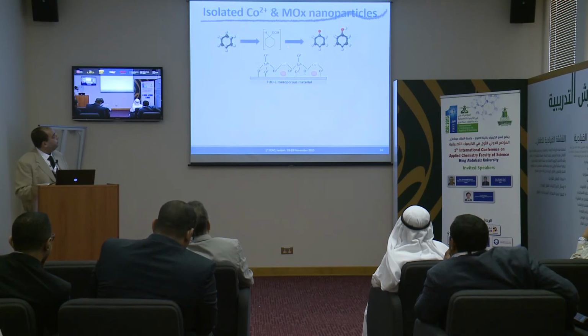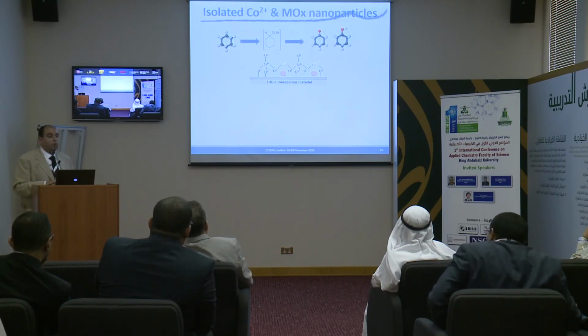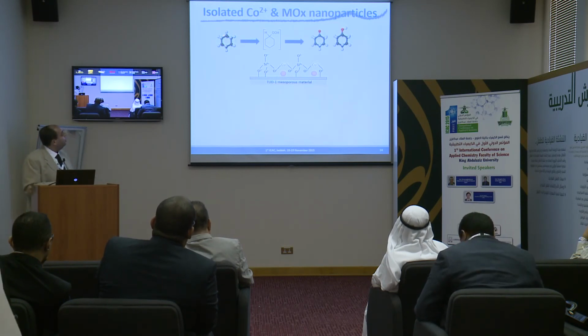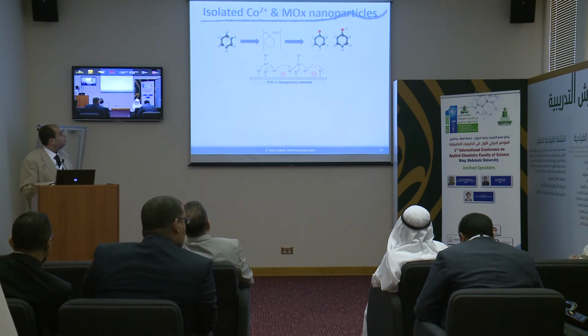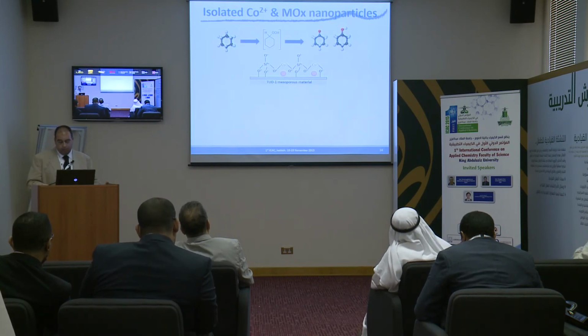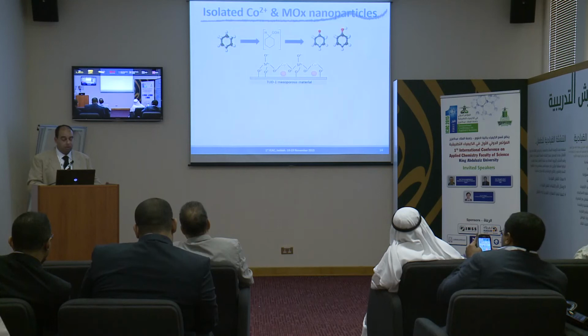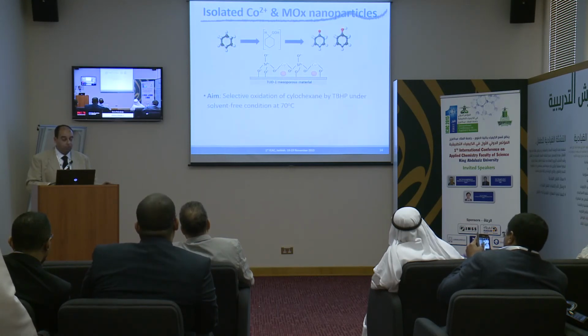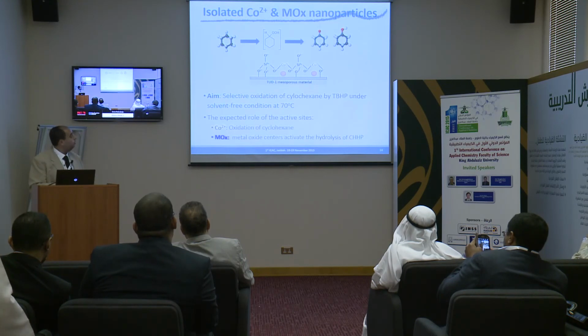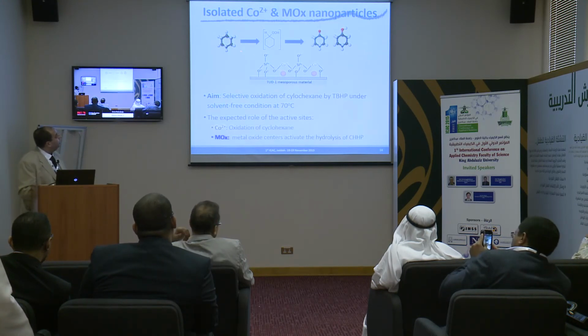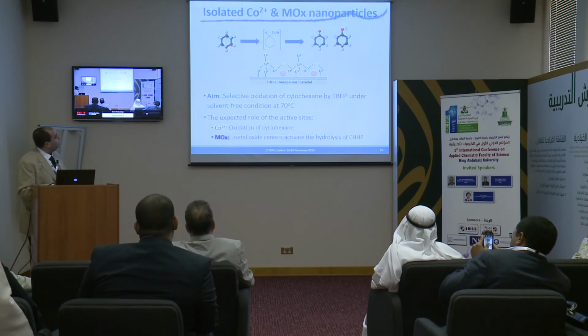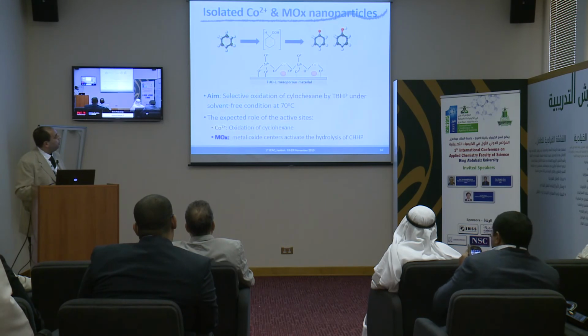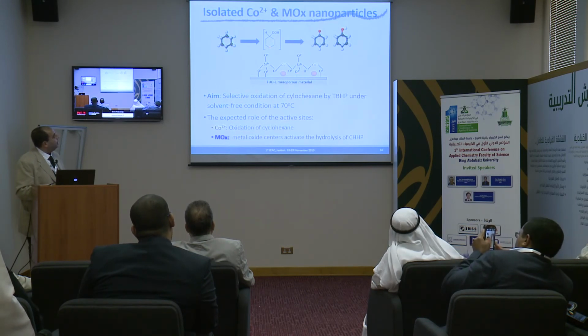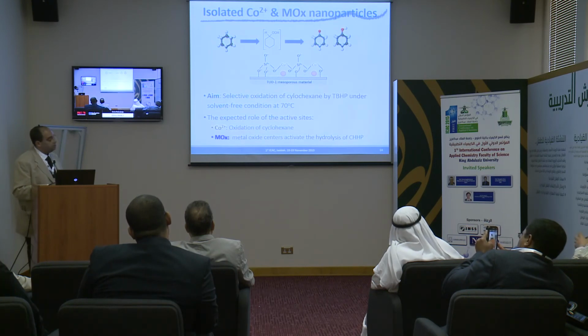Well, if you check in the literature, one of the mechanisms that has been proposed for this reaction includes the oxidation of cyclohexane to cyclohexyl hydroperoxide, which is going to be decomposed to cyclohexanone and cyclohexanol, and then over-oxidation reaction occurs to form different oxygenated products. But here we aim to design a catalyst like this, so the cobalt site will work to oxidize cyclohexane to cyclohexyl hydroperoxide, and the metal oxide center should facilitate the hydrolysis of cyclohexyl hydroperoxide to form the aldehyde and ketones.